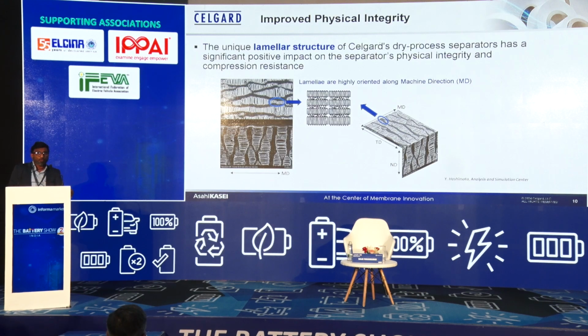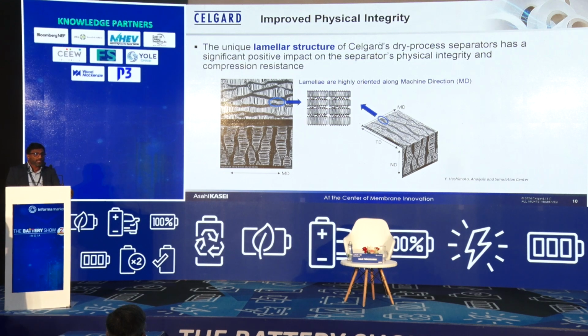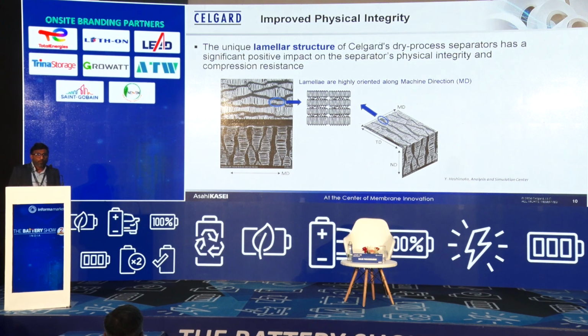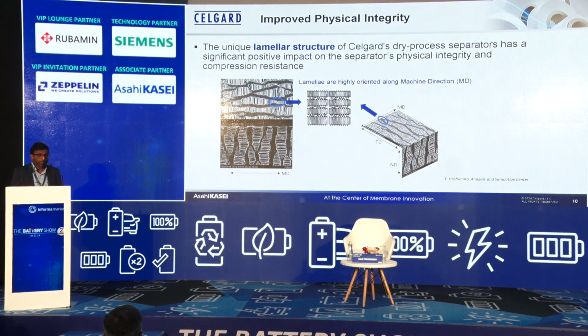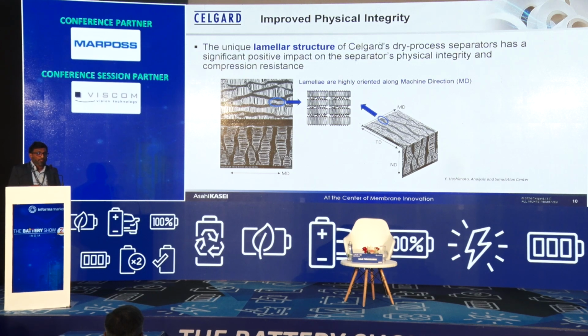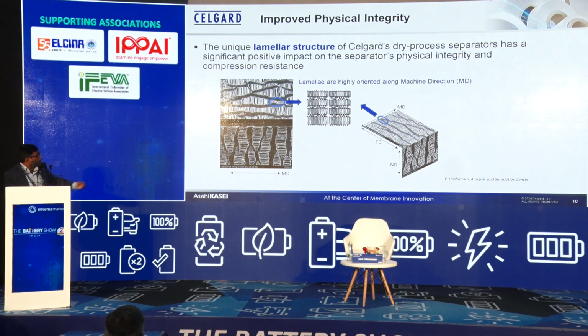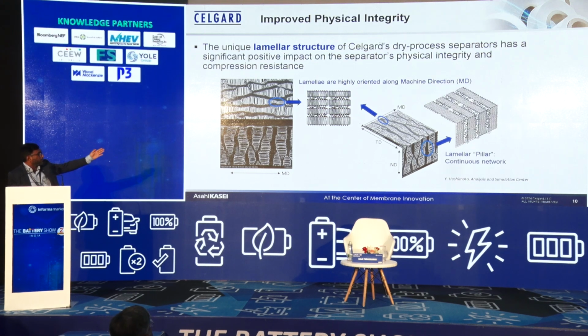The uniqueness of the dry separators is basically the lamellar nature. You have seen that the pore formation is basically by stretching the polypropylene in one direction. When you stretch the polypropylene in one direction, it forms pillars which give high mechanical strength to the separators, and also pores formed by the elongation of the material. So it is a combination of porosity and mechanical strength, which gives the separator the property to withstand a high amount of stress inside the cells. This is the lamellar structure you can see: you have the pores, and the pillars coming across.